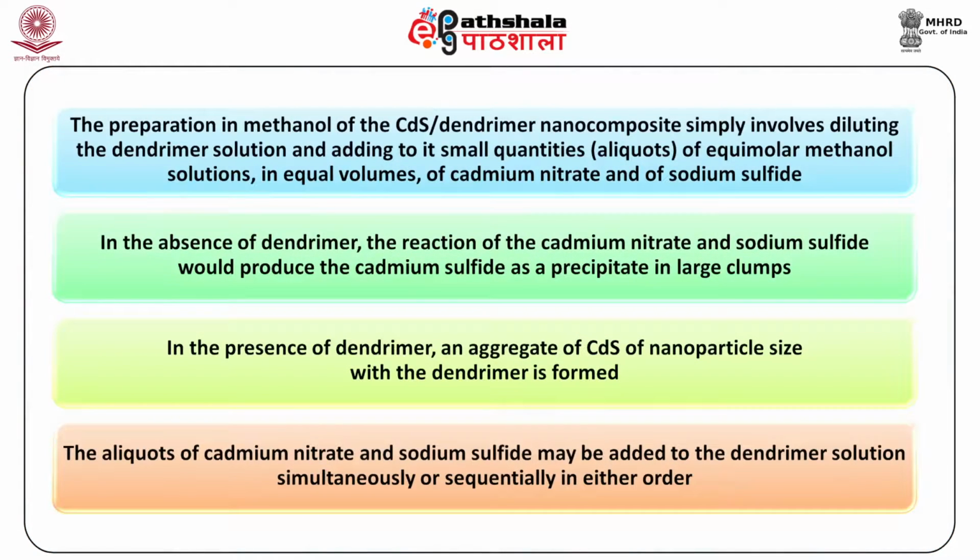The preparation in methanol of the CdS dendrimer nanocomposite simply involves diluting the dendrimer solution and adding it to small quantities or aliquots of equimolar methanol solution in equal volumes of the cadmium nitrate and of sodium sulfide. In the absence of dendrimer, the reaction of the cadmium nitrate and sodium sulfide would produce the cadmium sulfide as a precipitate in large clumps. In the presence of the dendrimer, however, an aggregate of the CdS of nanocrystal or nanoparticle size with that of the dendrimer is formed.